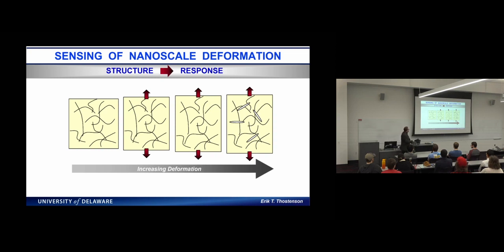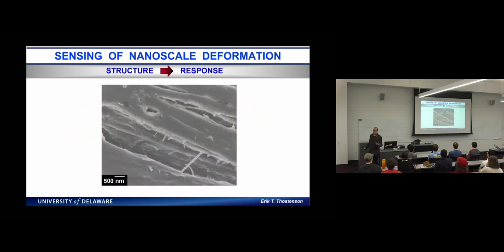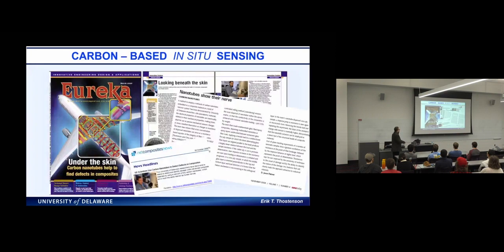As we stretch it, these tunneling gaps change, and then if you get a crack, that permanently severs the conducting network. When we first published this work, it drew a lot of attention, and I think it's a very practical application of nanotechnology. Nanotechnology is often abstract, but this is very practical. You see this is a very small crack, but we see these individual conducting carbon nanotubes protruding into the crack. In order to sense a microscale crack, you need a nanoscale wire. Okay.